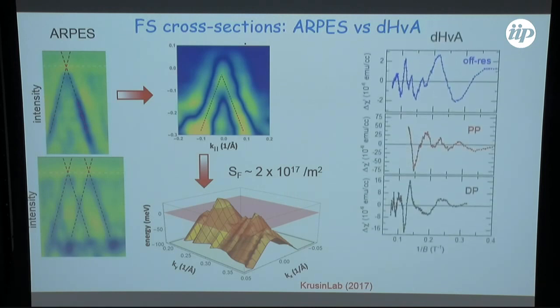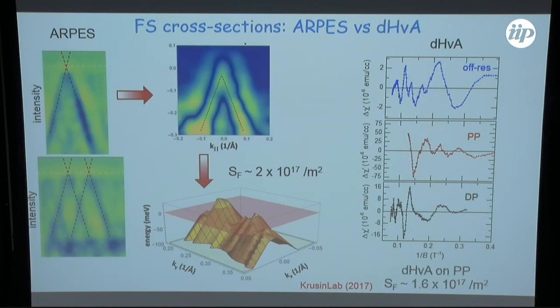And this is our data on the same samples, the de Haas-van Alphen data, where we look at quantum oscillations. And this notation I will explain in a moment. But basically, they give essentially the same Fermi surface cross-section, which corresponds to a bulk carrier density of the order of 10 to the 17, which corresponds to a surface carrier density of about 10 to the 13 per centimeter squared, which is very low.